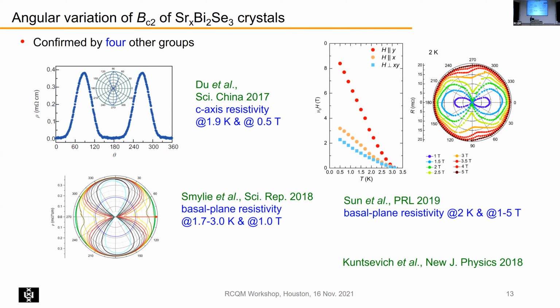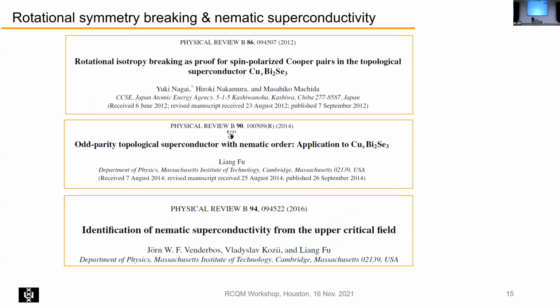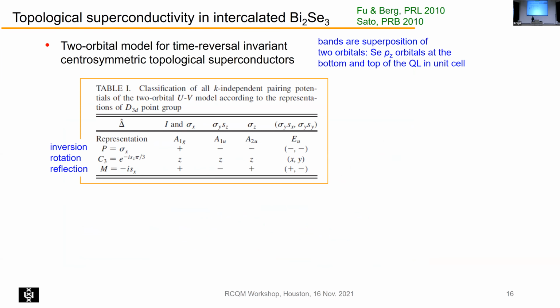Now I want to go to the theory, and actually there are a number of papers already before this work was reported that actually allude to this situation, that you could have this rotational isotropy breaking, and that you have special Cooper pairs, and in particular there were papers that were actually trying to explain properties of copper bismuth selenium 3, but exactly the same for strontium. So an important ingredient there is a model by Fu and Berg, and actually they use a so-called two-orbital model, where you have actually the bands are due to the two orbitals of the selenium PZ orbital. So remember you had the van der Waals gaps, and you have the PZ orbitals sticking into these gaps, and they would form a kind of pairing potential.